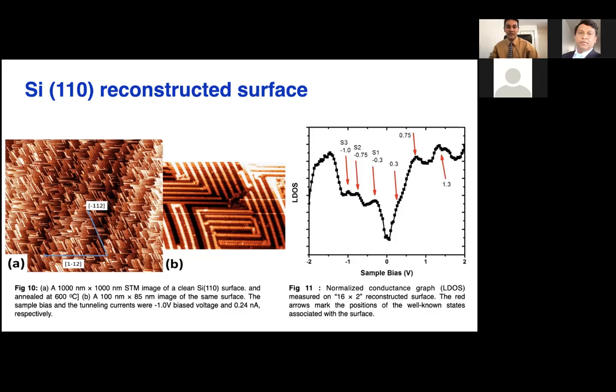This is the Fermi level, right? Below the Fermi level and above the Fermi level, there are surface states. The surface state S1 is a surface state for the silicon 110 reconstructed structure that can be attributed to the pentagon structure of the surface. What does the pentagon structure mean? On the silicon 110 surface, 4 atoms and 1 atom from the top layer combine together and form a pentagon-like structure. That is why we call it the pentagon structure. This surface state S1 is because of the pentagon structure.